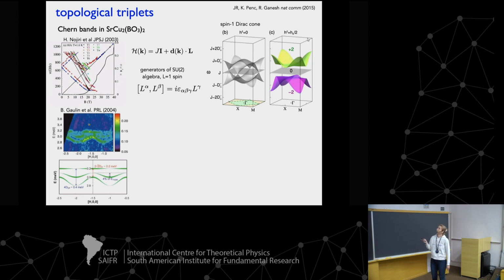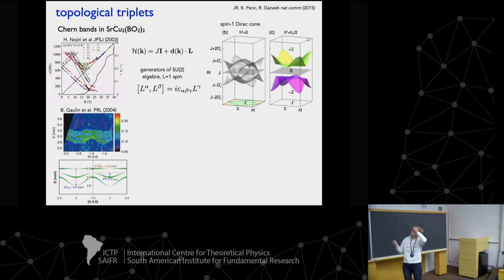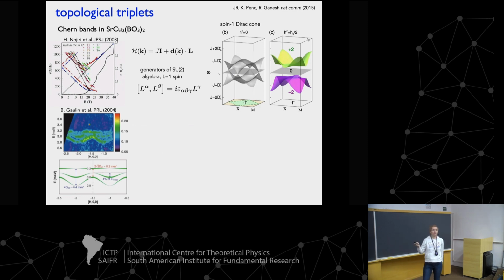As it turns out, one can use magnetic field to tune the system into a topologically non-trivial band structure. So when we are here, it's actually very small. I'm sorry, I should have zoomed in. When the field is very small, less than 1 Tesla, we have these topologically non-trivial bands. And this point here, where the bands cross again, is a topological transition from the non-trivial bands to the trivial bands. So that's a Dirac cone already measured in the ESR spectrum.